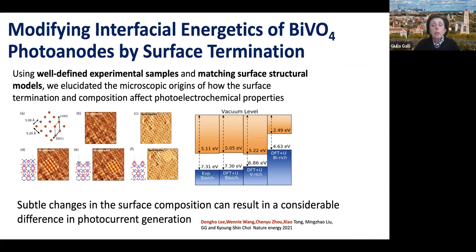So what did we do? We created different surfaces and we computed several STM images. These are the images here on the left. Then we created different surfaces, stoichiometric, vanadium rich, bismuth rich, and so on and so forth. And we compared with experiment.